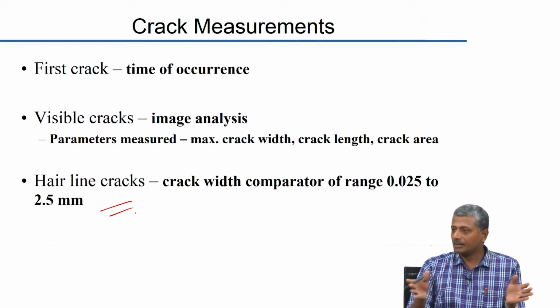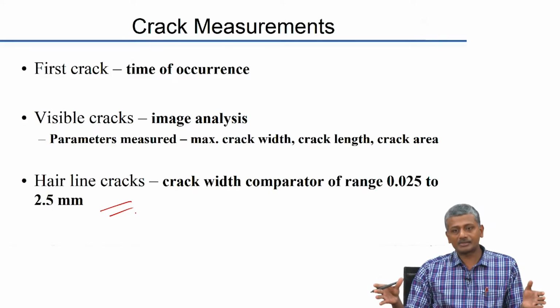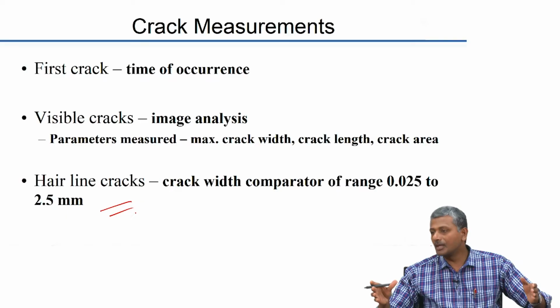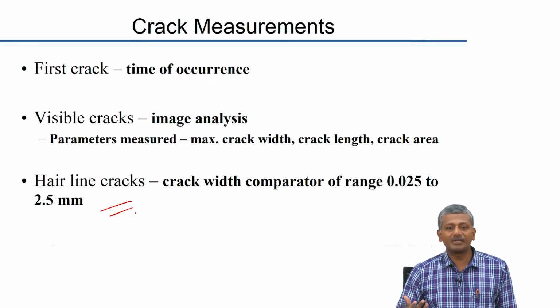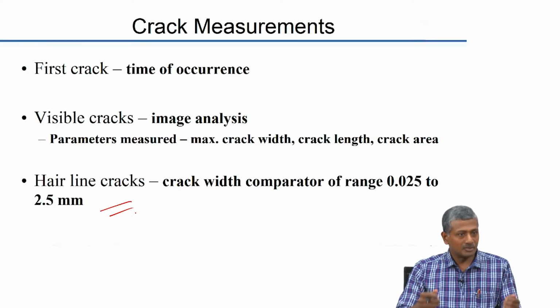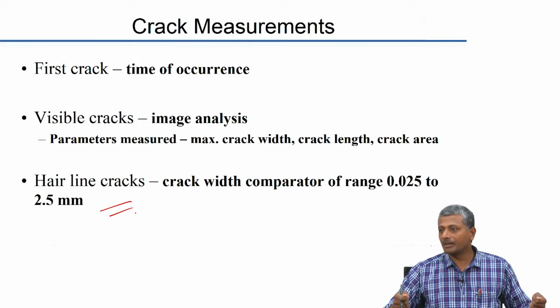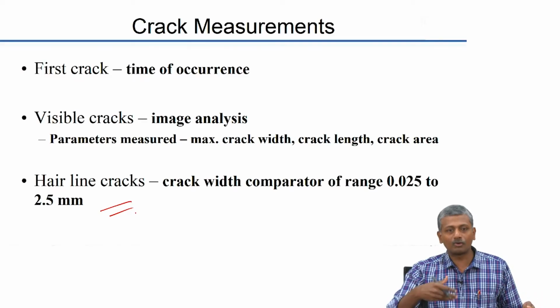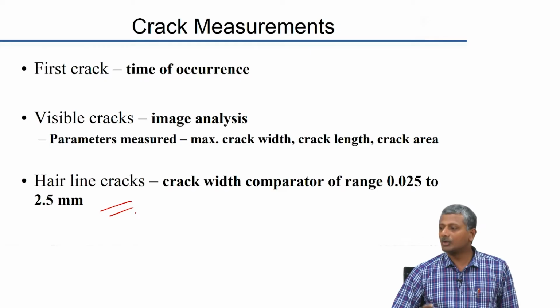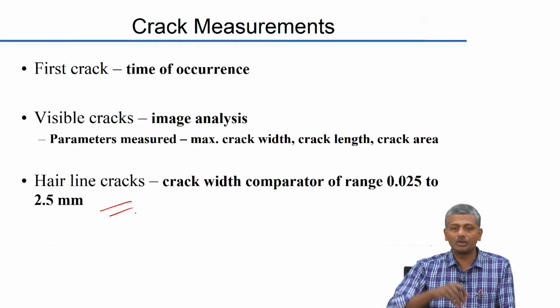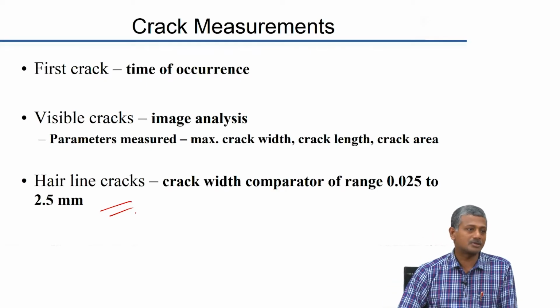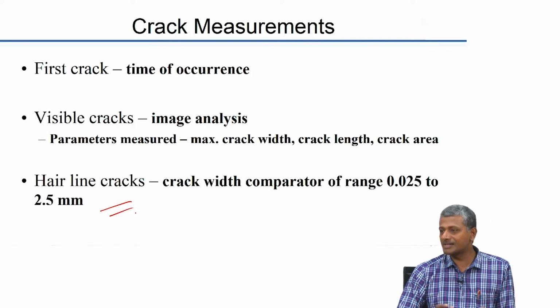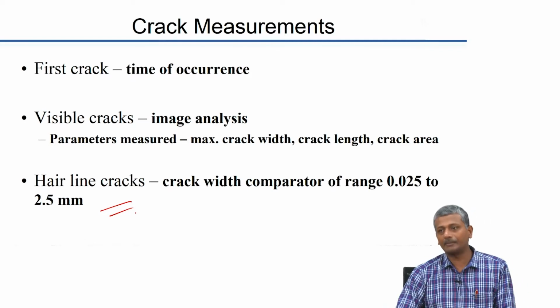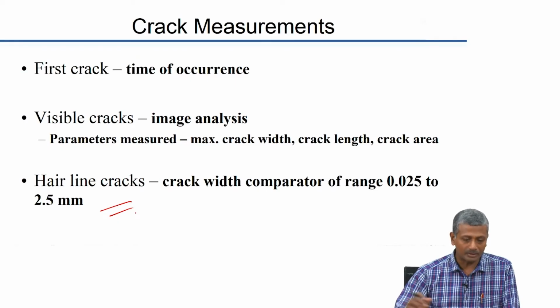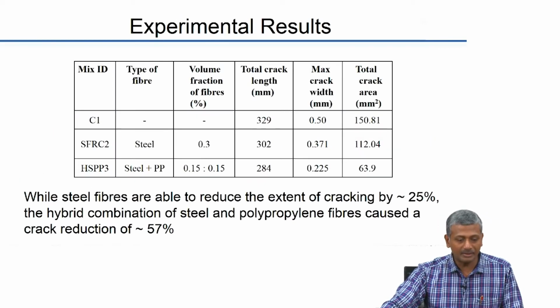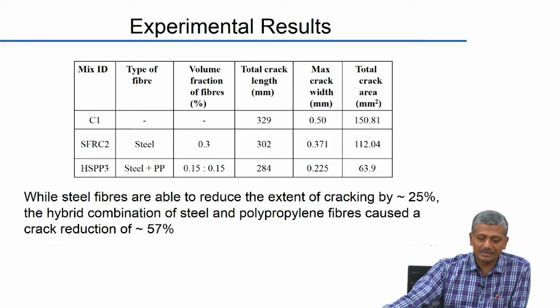So, this entire slab was sitting inside the environmental chamber. Of course, we had a very rudimentary setup. We had to actually remove the slab from the chamber and then visually look for any signs of cracking, okay. You can automate this process also by putting a video camera inside and looking at the occurrence of the cracking, okay. But in this case, it was visually done by removing the slab from time to time and checking the occurrence of crack. So, there might be some errors in that.